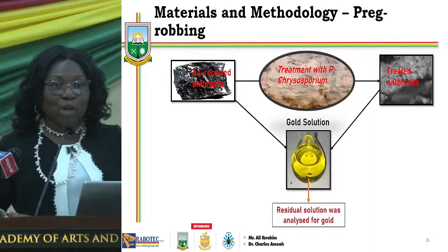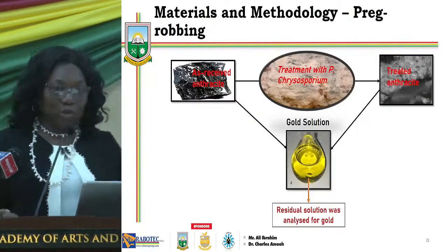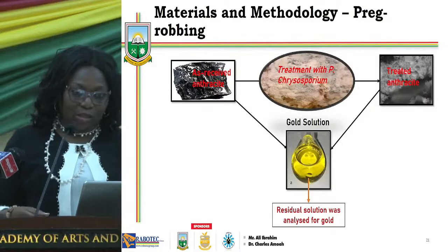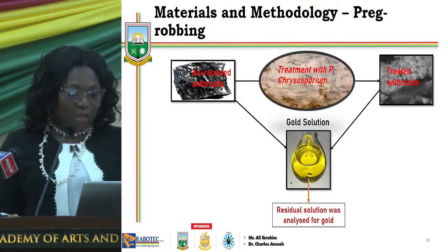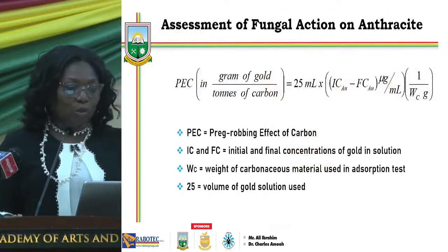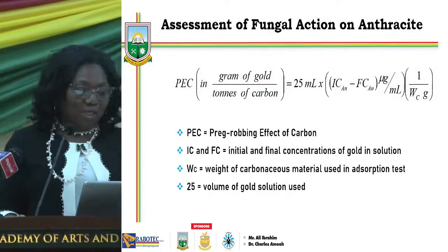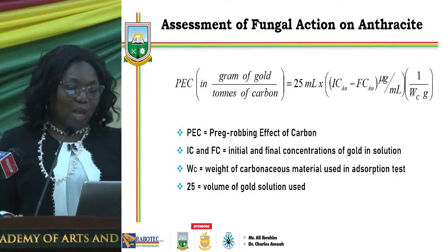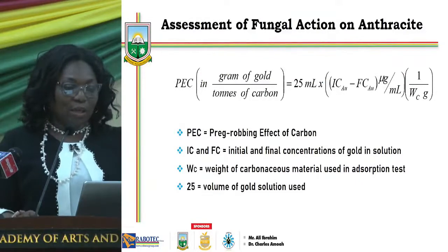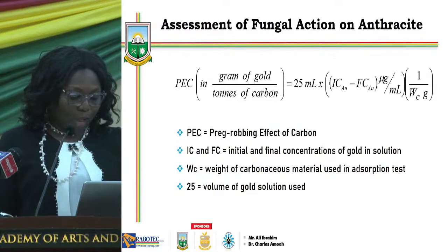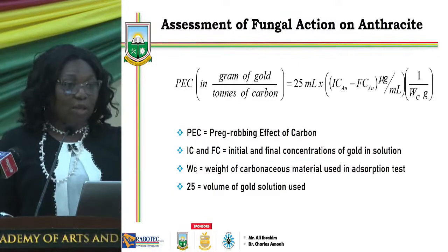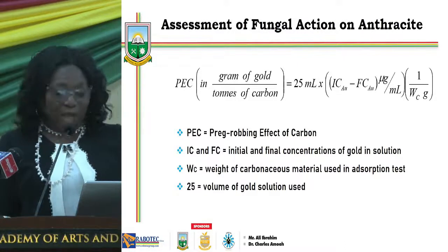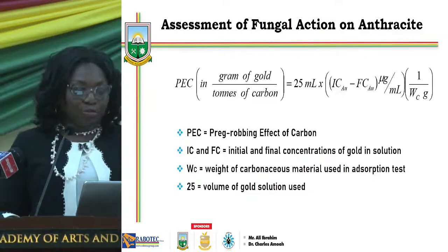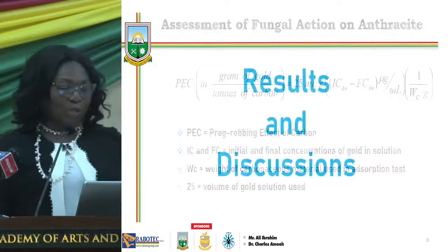The residual concentration of gold in solution was checked to find out how much has been adsorbed onto the carbon. And this equation was used to calculate in gram per ton how much the anthracite has absorbed before and after the treatment. So I'll show you some results.